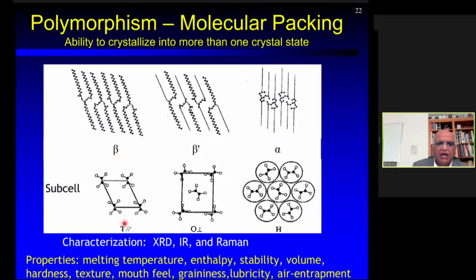For example, in beta, these zigzag chains are in parallel configuration, whereas in beta prime, they are in orthorhombic perpendicular arrangement to each other, whereas in alpha, they do not have any specific chain-chain interactions, but they are arranged in a hexagonal packing, which is shown here. And the packing along the long axis is shown on the top. These molecules pack in a bilayer structure, as is shown here, with 2 chain lengths. Each of these polymorphs have different properties, which I'm going to show you, and based on those properties, their functional properties also differ.